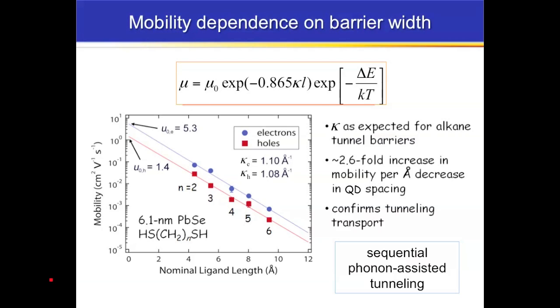And so we are able to use this kind of approach to tell that at room temperature, the charge transport mechanism in our film is basically sequential tunneling, where you get tunnel transport from dot to dot, 1 dot at a time. And it's phonon-assisted, meaning that we've got energy levels that are slightly different from each other from dot to dot, because we always have a finite distribution of sizes within our films. And so phonon-assisted tunneling is really the active mechanism.